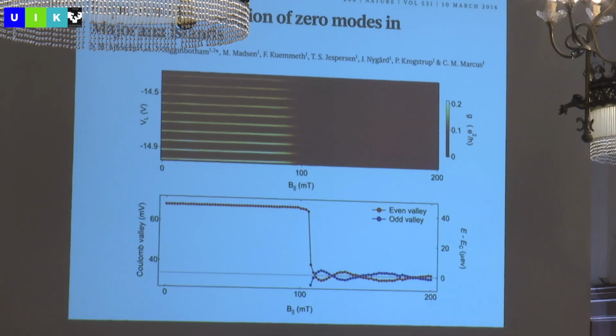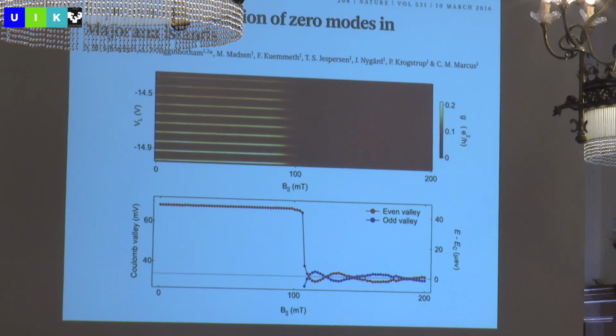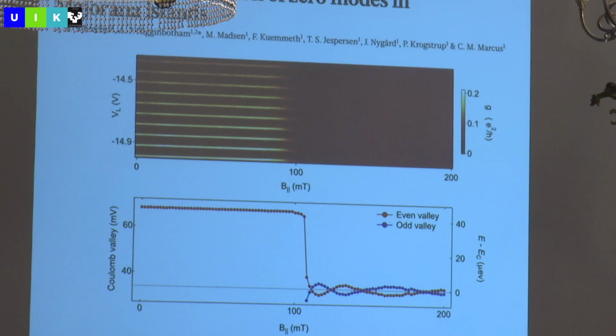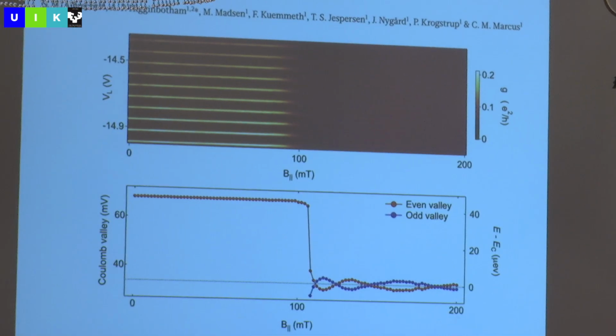I can keep very careful track of the spacing of those Coulomb blockade peaks, and I notice something remarkable. When they're 2e spacing, and I measure the spacing between Coulomb blockade peaks, I've only got even peaks, so there's only a red curve, there's no blue curve. And then suddenly this drops by a factor of half, and it becomes 1e spaced.